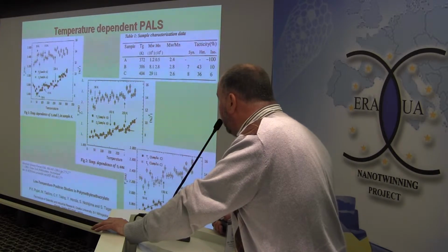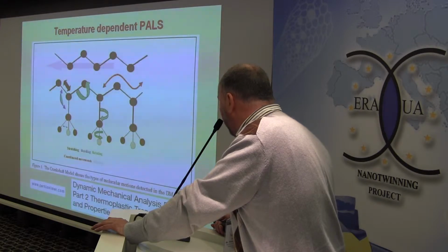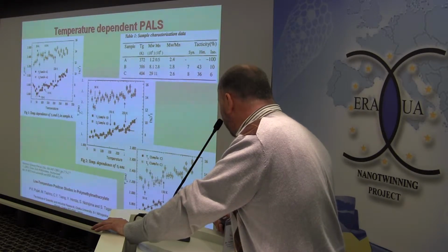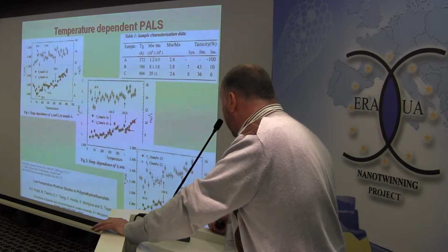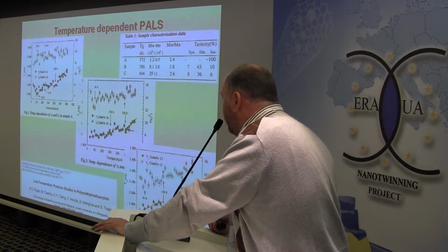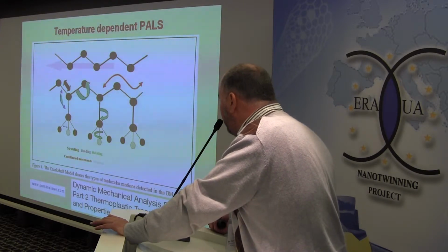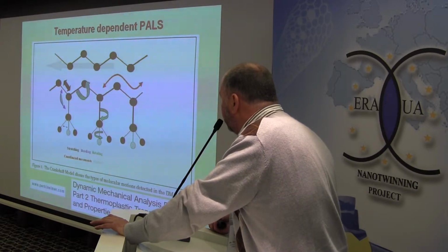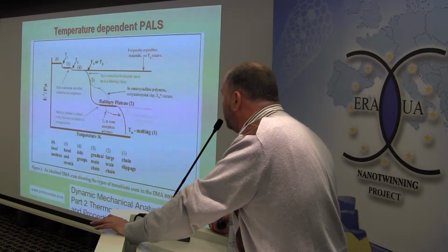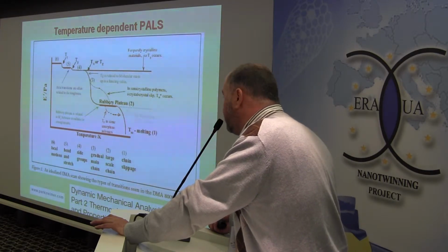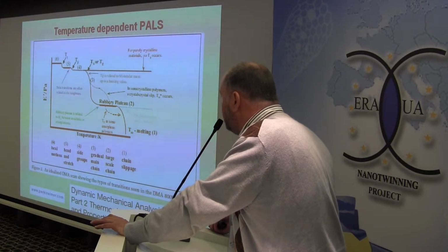They also found that for pure PMMA there are two critical temperatures near 150 and 250 K. The authors explained the results according to molecular motion in the polymer, in terms of gamma and beta transitions, which occur at temperatures below the glass transition temperature, Tg.